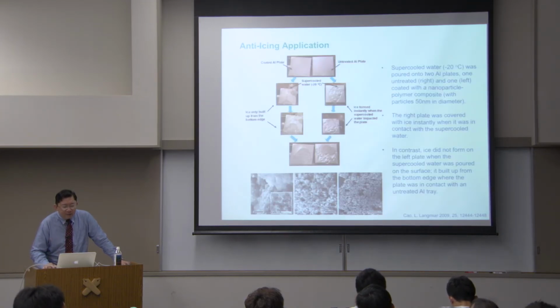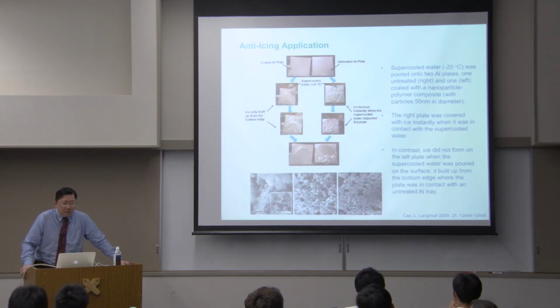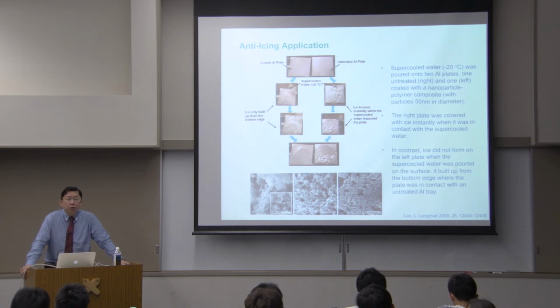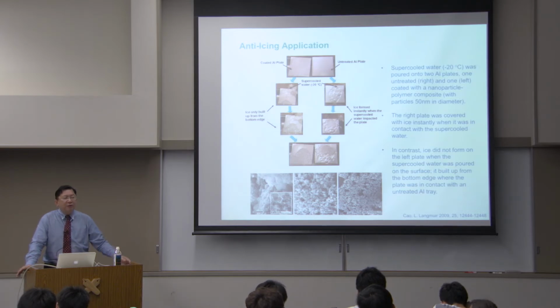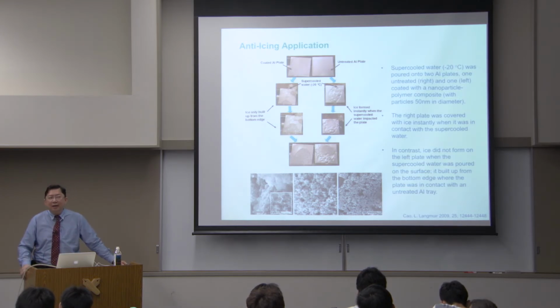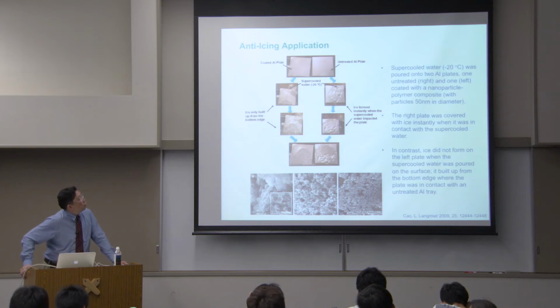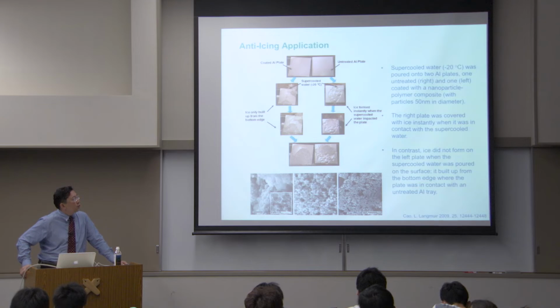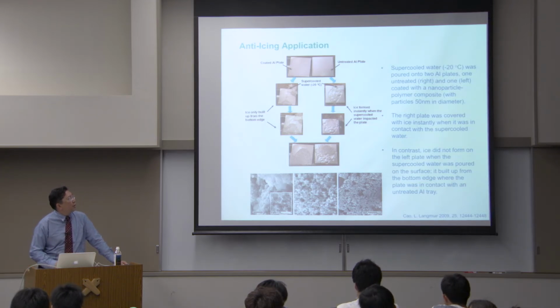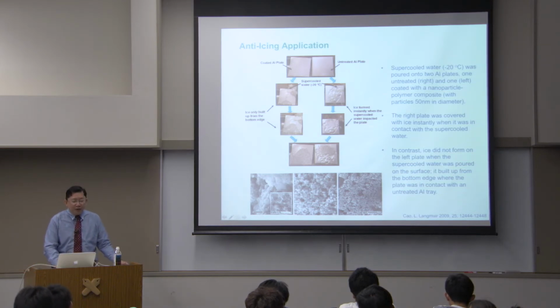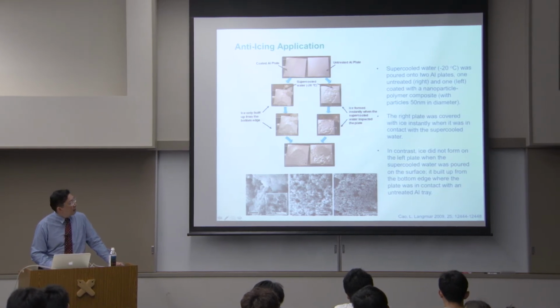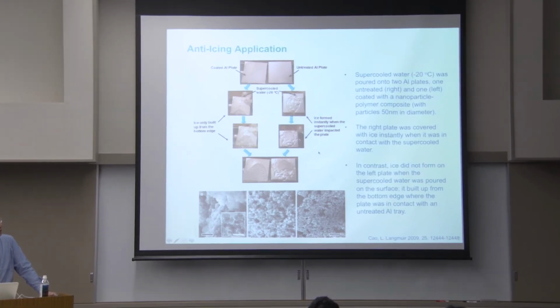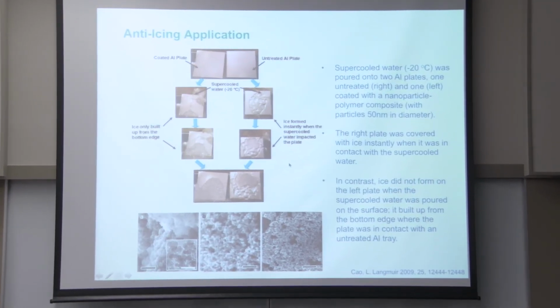This can be tested in several ways. One is direct exposure to an iced environment—put it in a refrigerator or in a snowstorm. Or you can use supercooled water, simply pour it on a surface, and observe whether ice forms upon exposure to the atmosphere, resulting in ice crystals or adhesion of ice crystals on the surface.